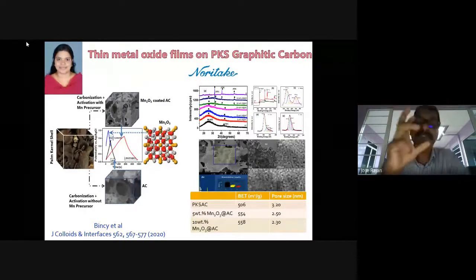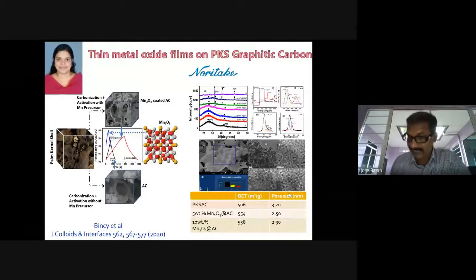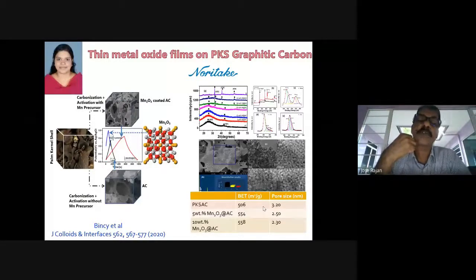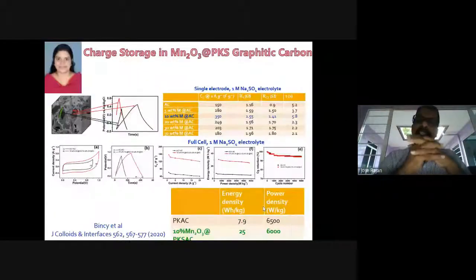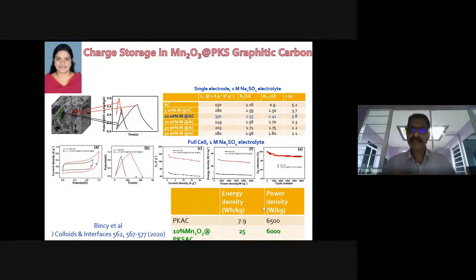on the surface of porous carbon, we got a surface whose surface area is compared in the table on the right side. You would see that the surface area of the metal oxide coated carbon is much higher than pure carbon, and its pore size is lower, so that it can accommodate charges and get them stored. This one compares the charge storability of this manganese oxide coated palm kernel shell graphitic carbon. The results are summarized in the table at the bottom.